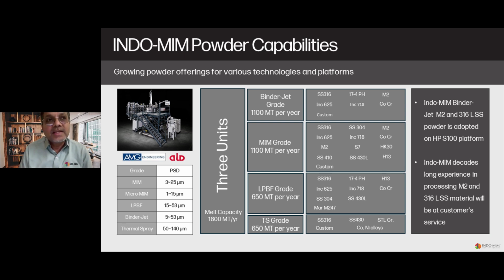But what sets us apart is that we also manufacture metal powder for additive manufacturing. Originally, we started making these powders for our own captive requirement for the MIM process, but then we expanded our capabilities into 3 gas atomizers, where we currently produce powders for binder jet, LPBF, thermal spray, cold spray, pretty much wherever metal powders are required, anywhere between 3 microns to 140 microns particle size distribution. We are in a position to make those powders.